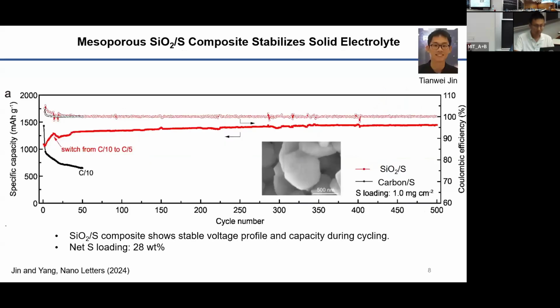So one day I asked my students, let's just get rid of carbon. Let's try the exact opposite. We tried silicon dioxide, which is insulating. So let's see how the performance is. And surprisingly, with this insulating matrix, which is also an mesoporous silicon dioxide with basically the same structure and pore size as the carbon matrix, we get a very steady cycling over 500 cycles.